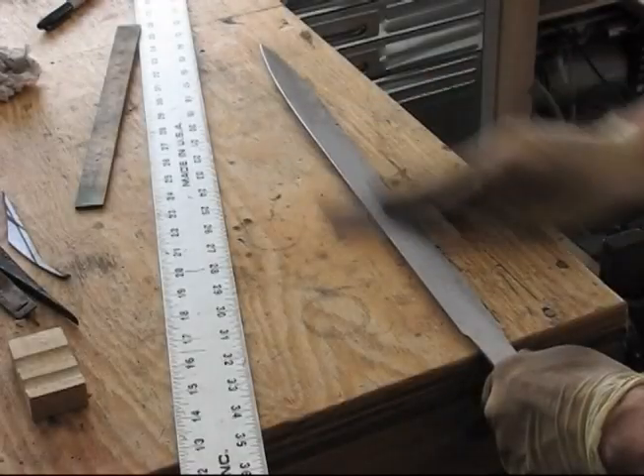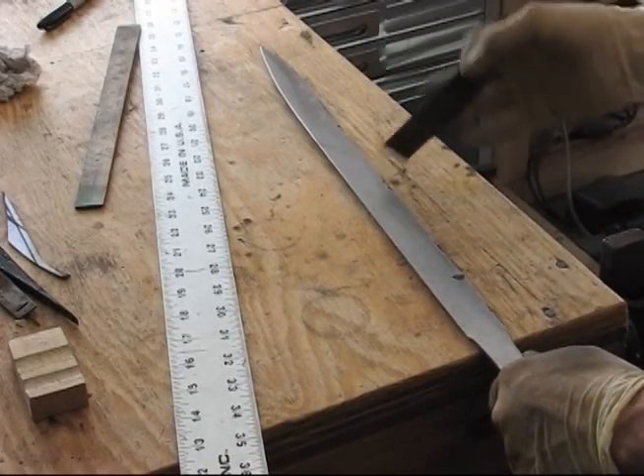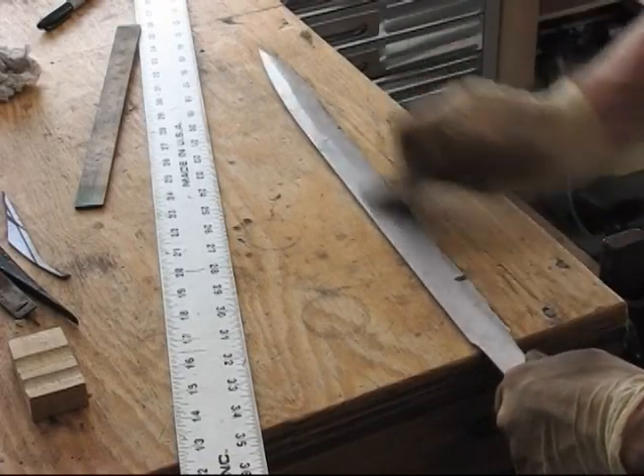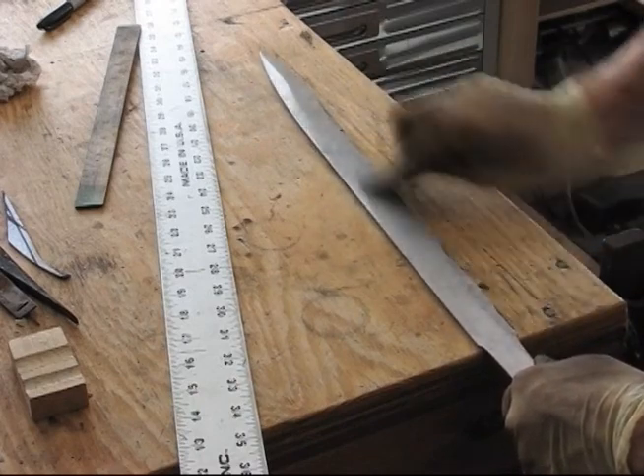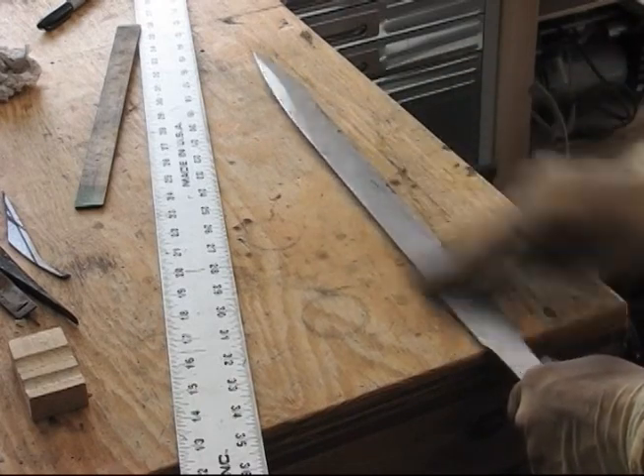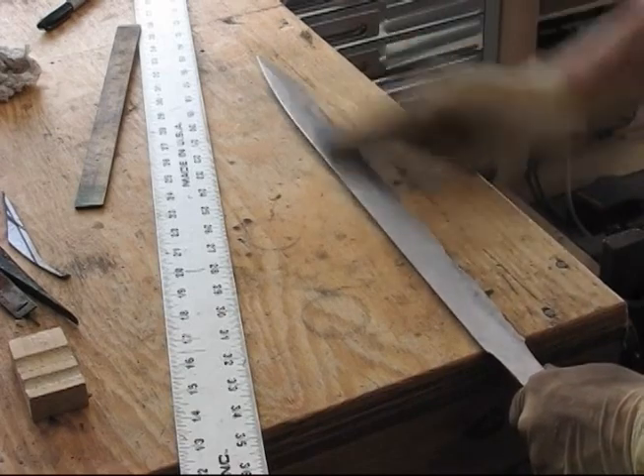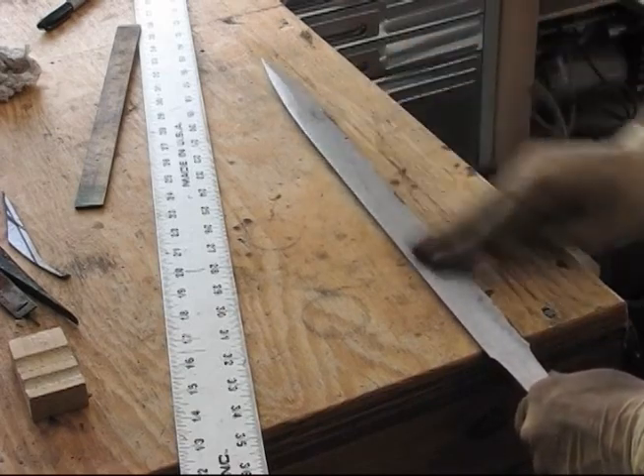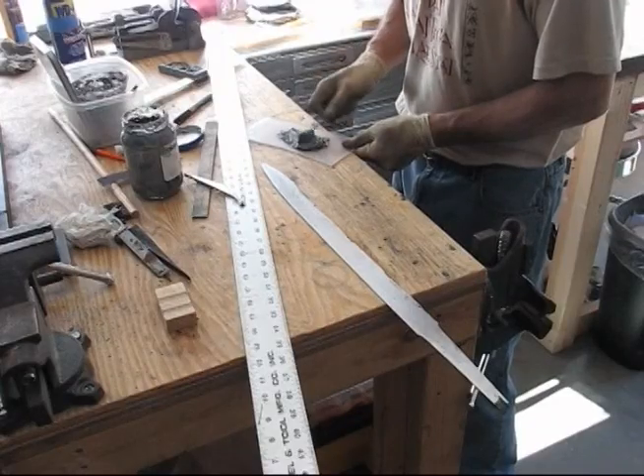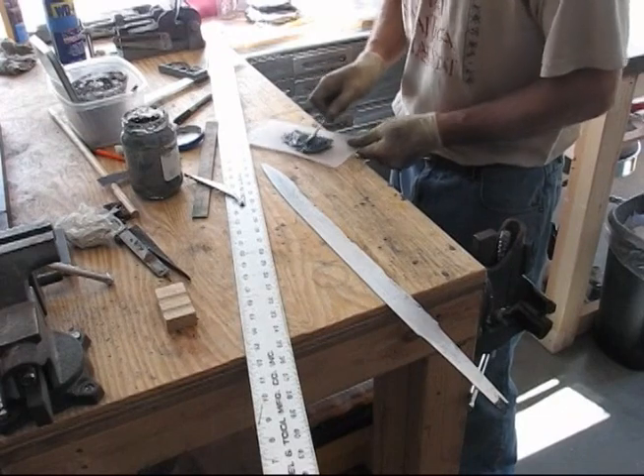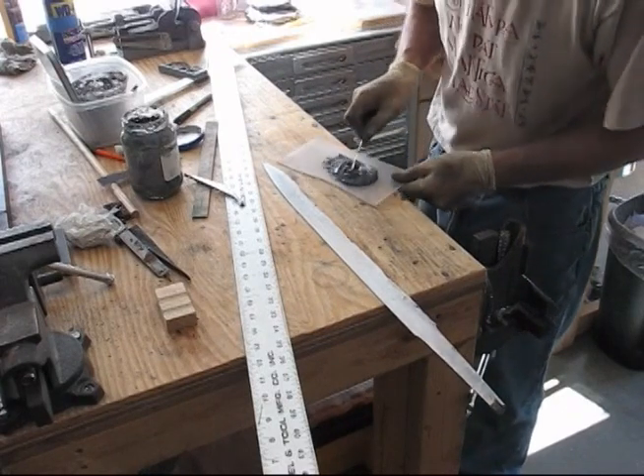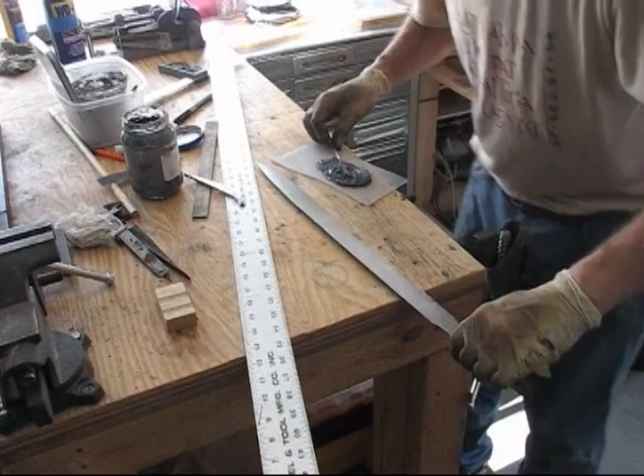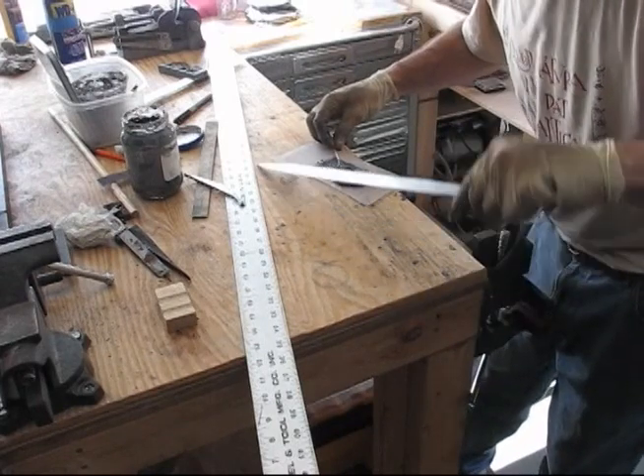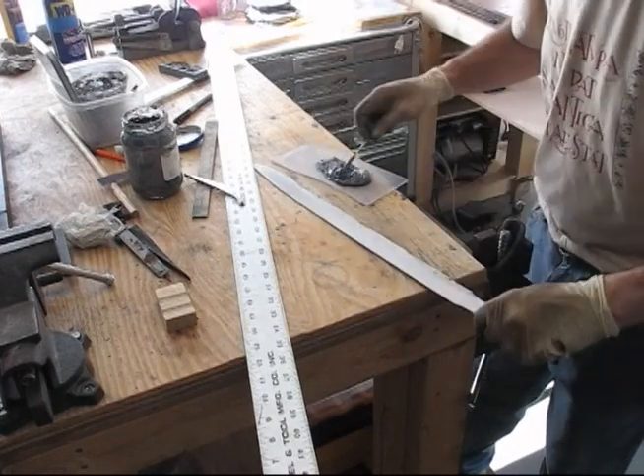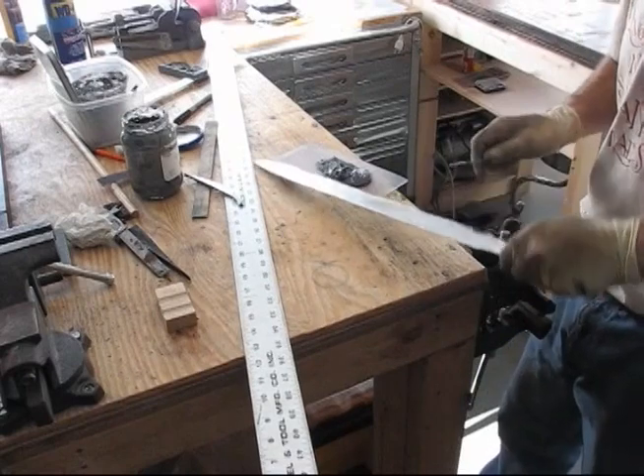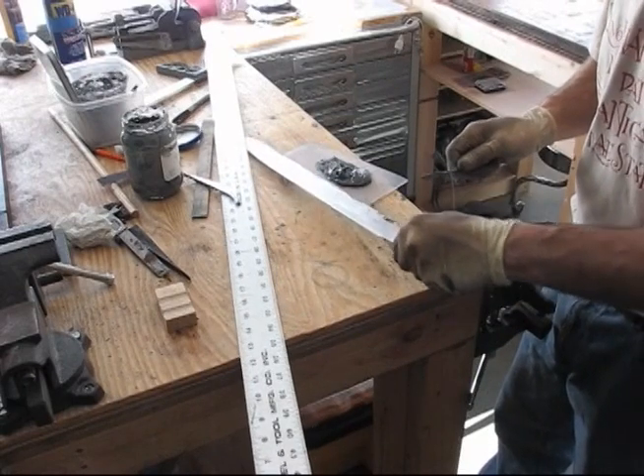Although claying a blade to control how far the edge hardens is a Japanese method, Jesus chose to utilize it here based on historical evidence of edge hardening in some seaxes. It is quite likely that this type of steel would have developed a natural hardening of the edge during quenching. Simple carbon steels like this one made in a traditional smelter are shallow hardening. By claying the blade, Jesus simply wanted to ensure that there would be no surprises.